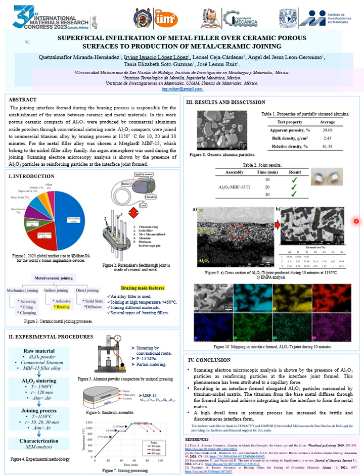The formation of an interface is shown in the cross-sectional micrograph. Chemical analysis with EDS-SEM at the bonding interface. According to the results, point 1 is associated with short aluminum oxide fibers that are dispersed in the metallic matrix. The white phase corresponds to point 2 and is mainly composed of titanium and nickel, with a smaller proportion of other elements. The phase with a gray color in point 3 has a high titanium content. The remaining elements at both points correspond to the MBF15 filler alloy that diffused during the brazing process.